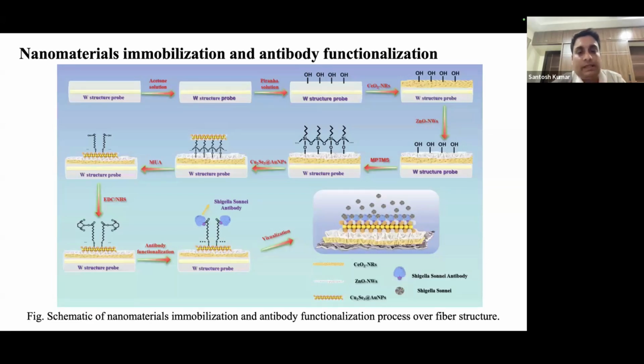So I hope you have observed that we have not used any high-end instrument for the coating process. We have just used the conventional method, and I'll show you the results. We got very good results with this. This is the advantage of this LSPR sensor over the surface plasmon resonance sensor, because in a surface plasmon resonance sensor we need to maintain uniform thickness, and if there is a change in the micrometer range, we cannot get a good resonance wavelength. But in LSPR there is no such issue. In this way we can coat the antibody easily on the fiber structure, and our sensor will be ready.